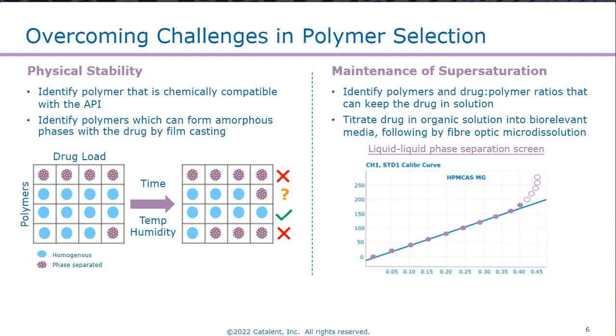And there's a screen that we use routinely here, a liquid-liquid phase separation screen, where we are using fiber optic microdissolution equipment, and in the dissolution medium we have the polymer pre-dissolved at a known level. We then titrate the drug into the dissolution medium, so the drug is dissolved in a water-miscible organic solvent at a high concentration. We titrate the drug in, and through monitoring the UV response and the scatter of the UV trace, we can determine when the drug is going to come out of solution, so either crystallizing or phase separating.